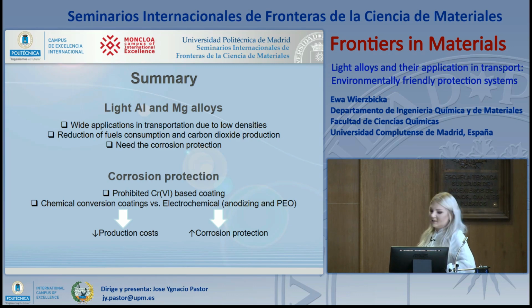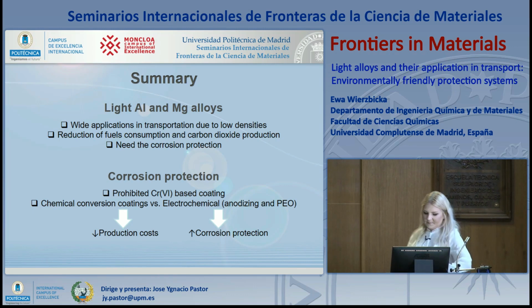And the corrosion protection, since the chromium-6 coatings are prohibited, can be in the form of chemical conversion coatings or electrochemical anodizing or PEO. The advantage of chemical conversion coatings is low production cost, and in the case of electrochemical anodizing or PEO coatings, it is higher corrosion protection. So this way, the level of protection can be adapted to the requirements.